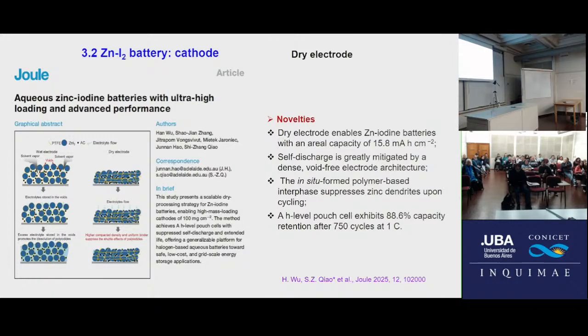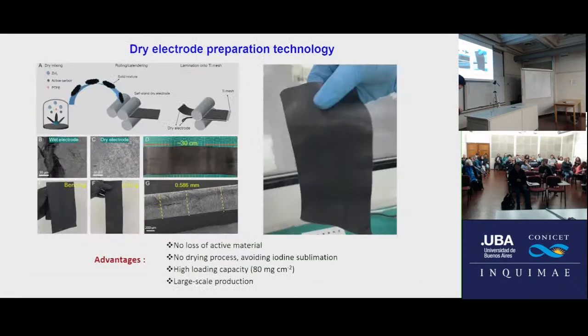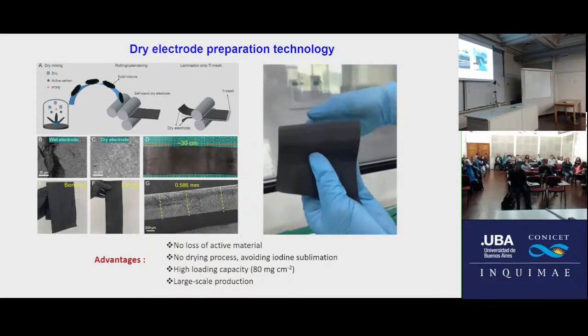Another method, we can use a dry method to produce electrodes. Most people use a wet method to produce electrodes. In that case, the area capacity is very low, as low as 6. However, if you use the dry electrode, it's very high, close to 16, right? So you can see performance is very good also. Okay, after 750 cycles, we can keep capacity at 89%. Okay, this is the video for this method.